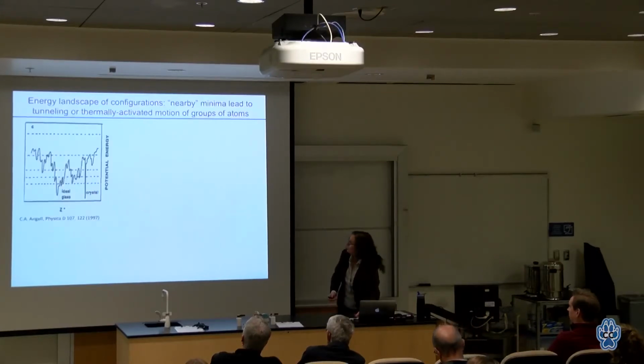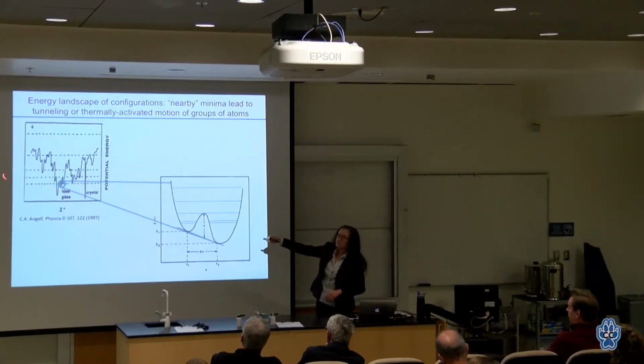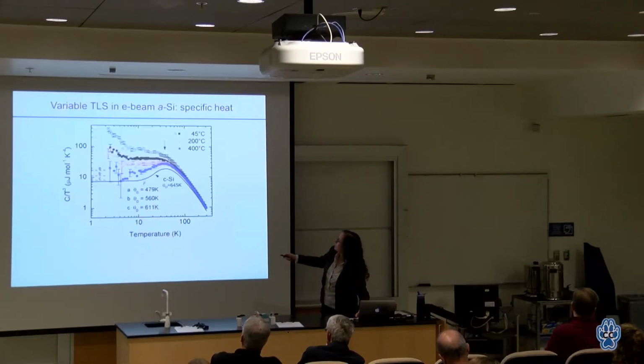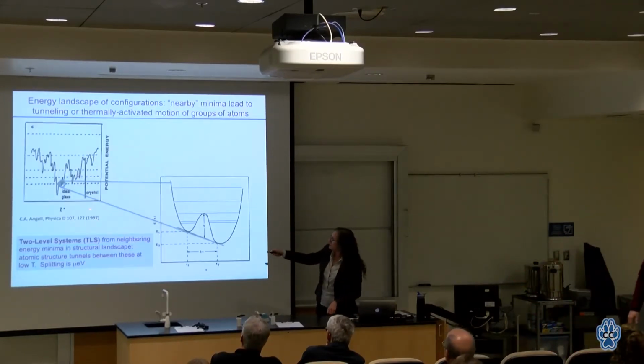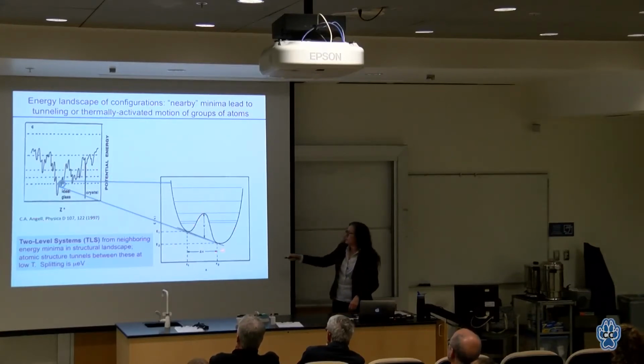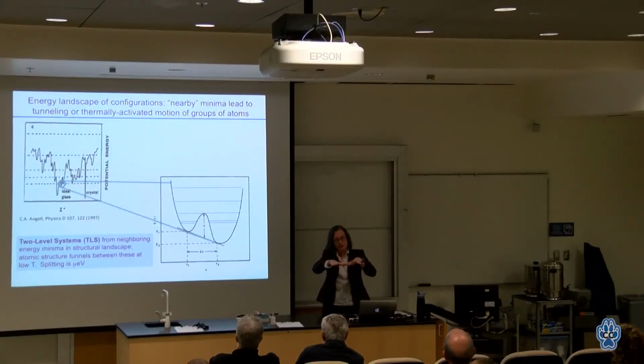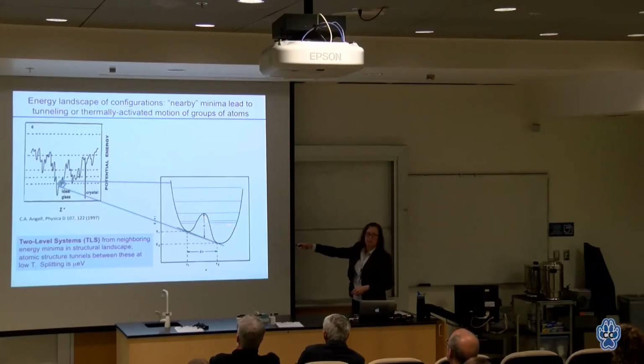So this was a huge mystery, and it was resolved, pointing back at that energy landscape I showed you before, and expanding that scale to here. There was a theory that was developed, actually not 1997, but more like in the 80s, what's called two-level systems. So the best description of that is that I have a whole bunch of atoms, and they can shift just a little bit from here to here, and it has to go over a potential barrier to do that. But because it can go from here to here, it will thermally activate, or it can tunnel. And because it can tunnel, you get an admixture of those two states. And that admixture of those two states is what you see in the heat capacity. That is the source of that extra linear term.